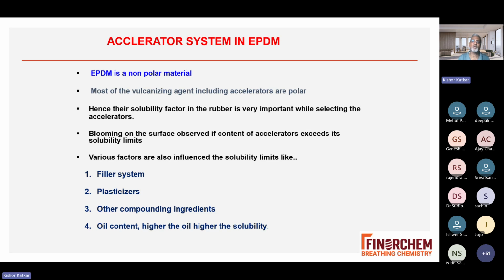EPDM has that problem, non-polar versus polar, and the solubility limit will come in the next slide. Stearic acid, microcrystalline wax, sulfur, and TMTD are a few names likely to bloom if you add more than the solubility limit. It is just like adding sugar to water: at normal temperature it dissolves up to a limit, if you heat it, it will dissolve more, but when it comes back to room temperature, the extra sugar comes out. That is called blooming, nothing else.